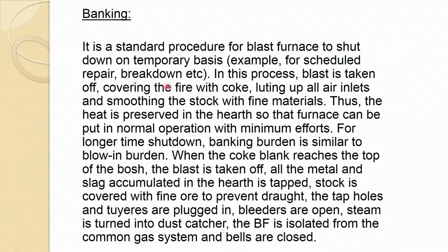So, you are covering your fire, or actually the stock, with the coke, just closing up all air inlets and smoothing the stock with fine material. So, you are preserving the heat. For a longer time shutdown, the banking burden is similar to the blow in burden. If you would like to shut it down for a much longer period, then the burden would be the same as we had in the blow in period. When the coke blank reaches the top of the bosh, the blast is taken off, all the metal and slag accumulated in the hearth is tapped, the stock is covered with fine ores to prevent draught, the tap holes and tuyeres are plugged, bleeders are opened, steam is turned into the dust catcher, the blast furnace is isolated from the common gas system and bells are closed.